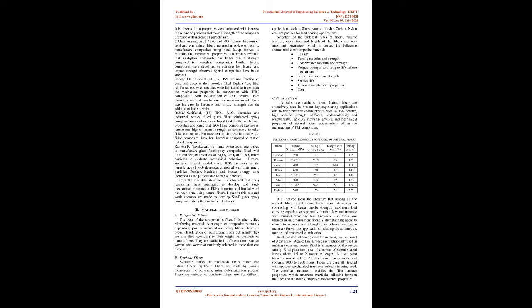Sandeep Kumar et al. [11] studied the erosive behavior of fiber reinforced hybrid composites consisting of vinyl ester resin and short E-glass/carbon fiber at different fiber weight fractions. Control factors were investigated using a Taguchi orthogonal array design to minimize the erosion rate with respect to impact velocity, impingement angle, and size of erodent, keeping other factors constant. The mechanical properties were evaluated to determine possible correlation with the erosion rate of these composites. The storage modulus steadily increases up to 3,927 MPa for 48% fibers, but on further increase in the fiber content, the value decreased to 3,321 MPa at 0 °C.